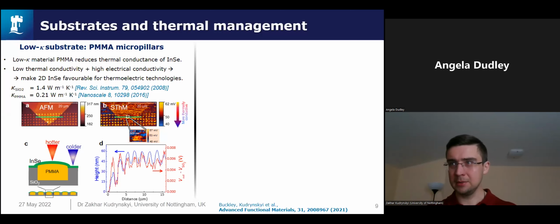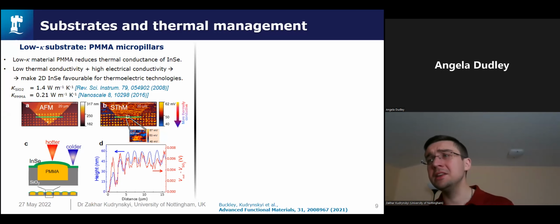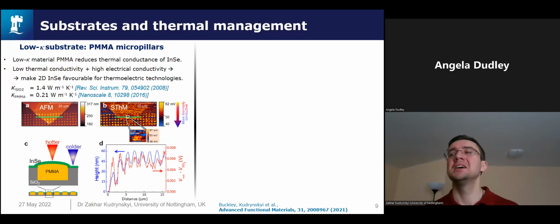So it means that by using a material with low thermal conductivity as a substrate, we can reduce the ability of a 2D material to dissipate heat and thus reduce its thermal conductance. This lower heat transport is a limiting factor in thermal management, but can be beneficial for thermoelectrics, where materials with high electrical conductivity and low thermal conductivity are needed. It should also be noted that PMMA is widely used in device fabrication of 2D materials, and the remaining residues can substantially distort thermal transport, leading to overheating.